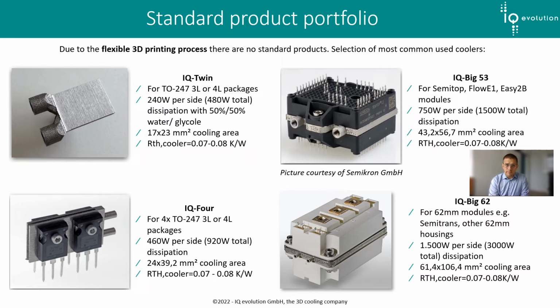I often get asked about a standard product portfolio. If you will, we have various coolers which are built for industrial standard discrete and module packages, such as TO247, Flow E, and 62 millimeters. You can see that we can cool from 240 watts per side to 750 watts for the Flow E to even 1500 watts per side for the 62 millimeters. And we expect an RTH of 0.07 to 0.08 Kelvin per watt.